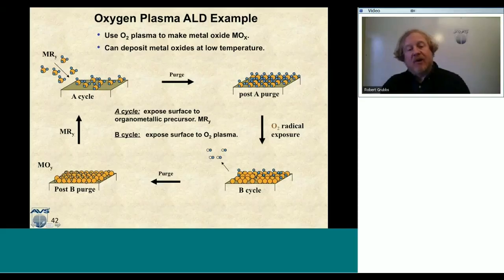Once I do that, I purge that away, and then this surface is ready again for my organometallic precursor to come down in. And again, it might sit in a physisorbed well. It actually might chemisorb to the surface. But the idea being is I do that, and then one of my exposures is an oxygen radical exposure, oxygen plasma exposure, and then I oxidize the surface, and at the same time, remove any of the byproducts, probably carbon dioxide and water from the surface.